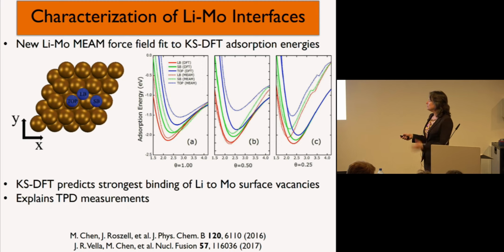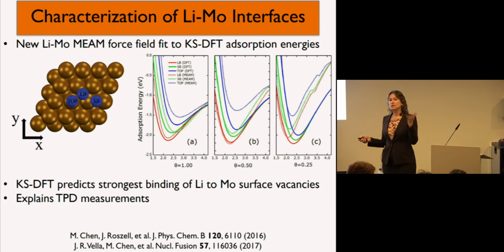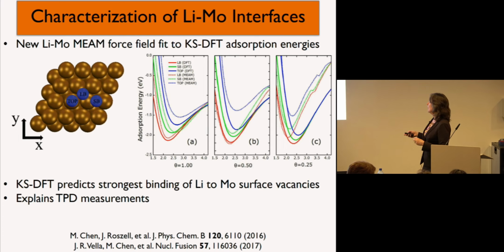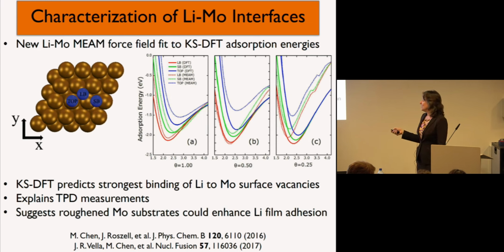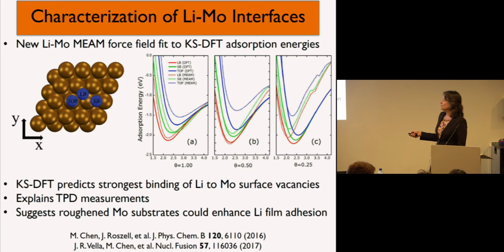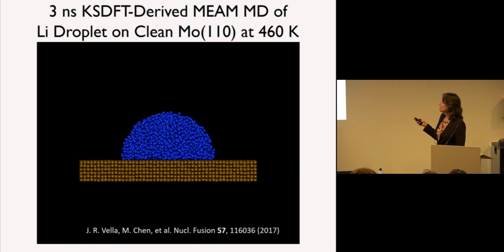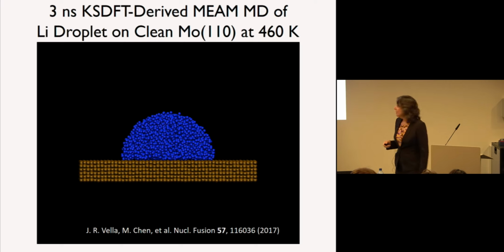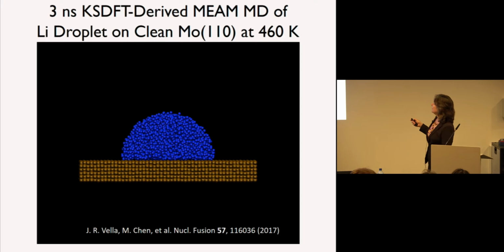And that actually helped us, I'm not showing the data here, understand thermal desorption experiments that were done to look at lithium desorbing from molybdenum. Basically, there were multiple peaks, the highest temperature peak corresponding to these vacancy sites. And what it suggested is that one could start to use roughened molybdenum substrates to help enhance the film adhesion going forward in these reactors. So we used that Kohn-Sham derived embedded atom method potential to do molecular dynamics of a lithium droplet shown here.